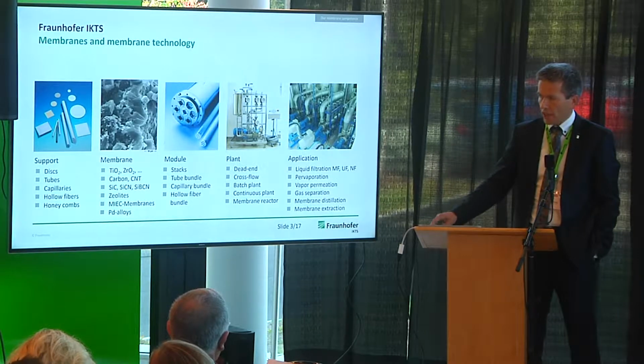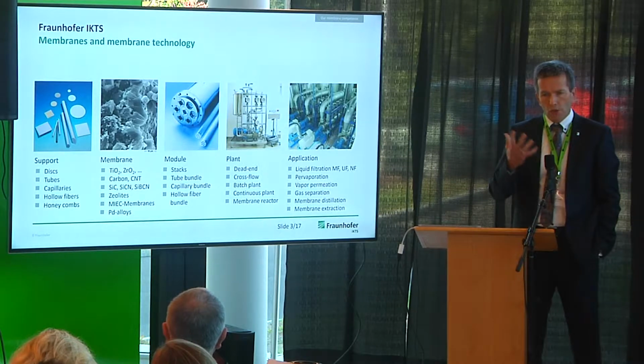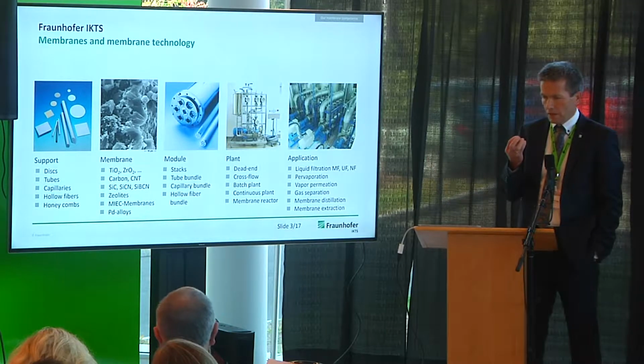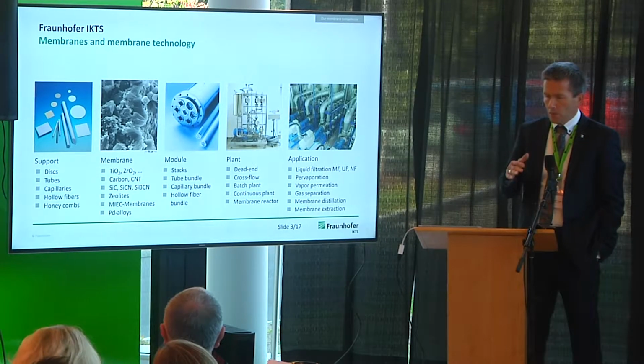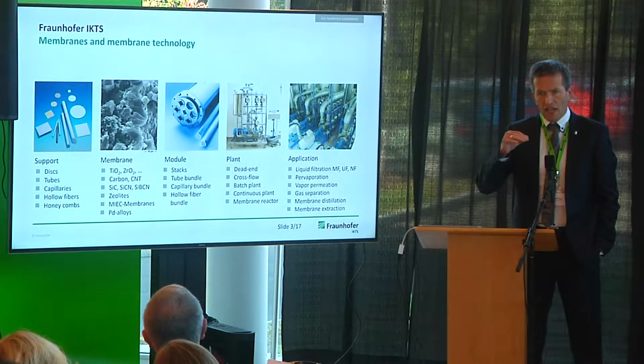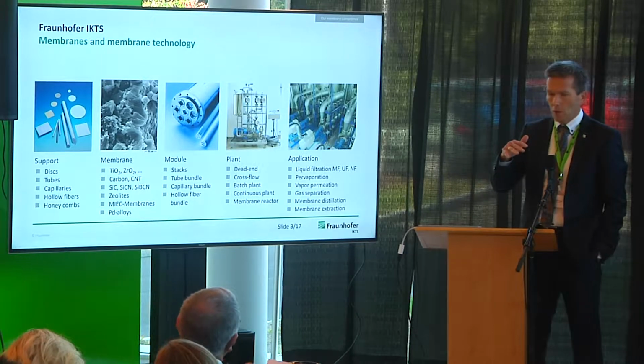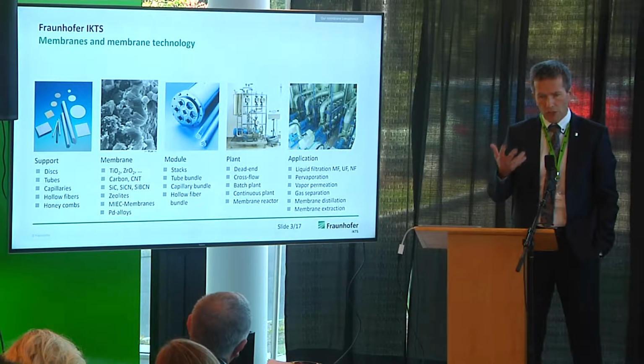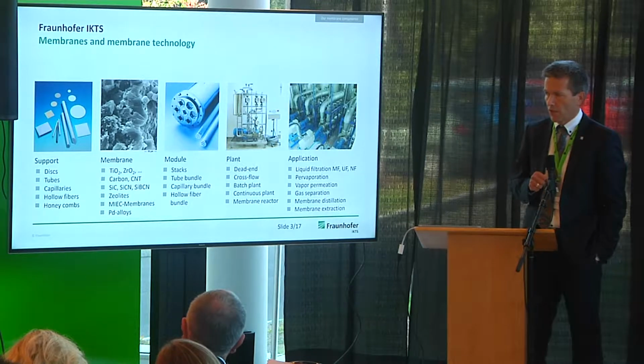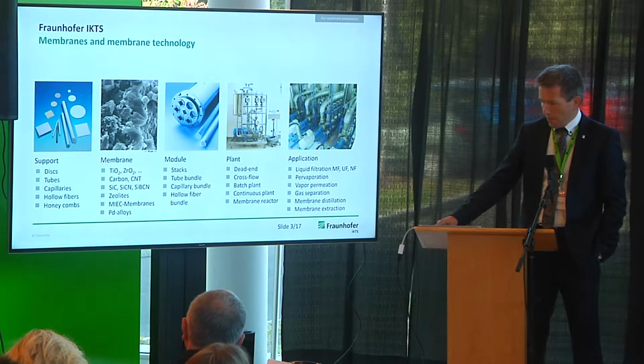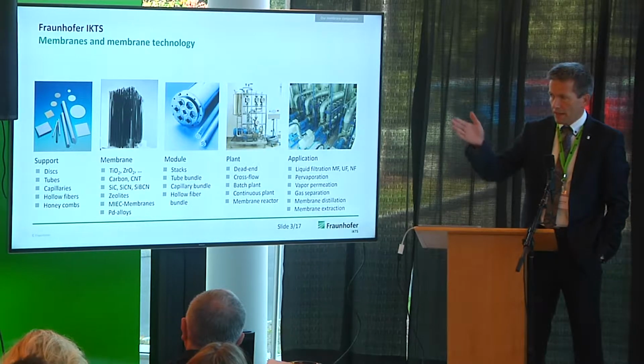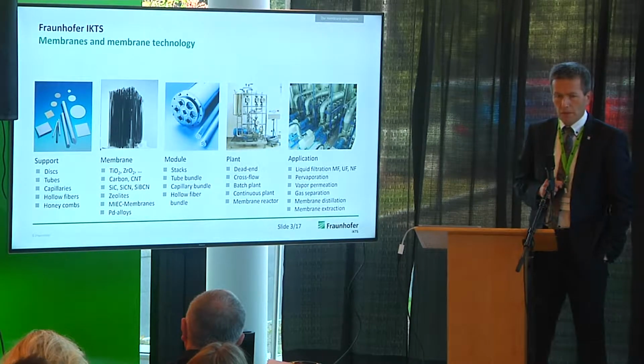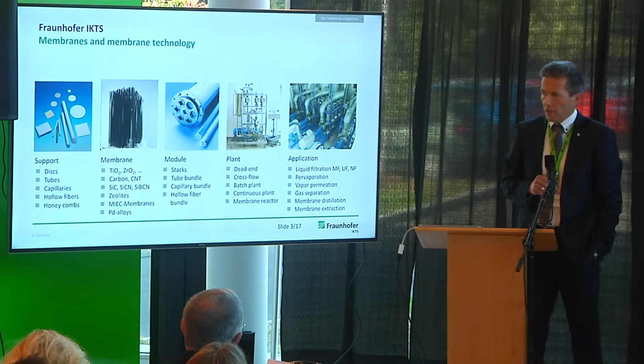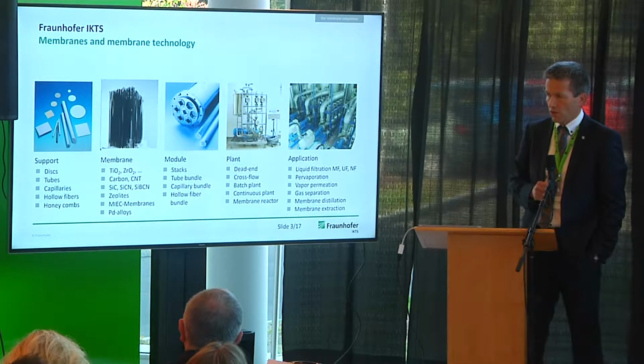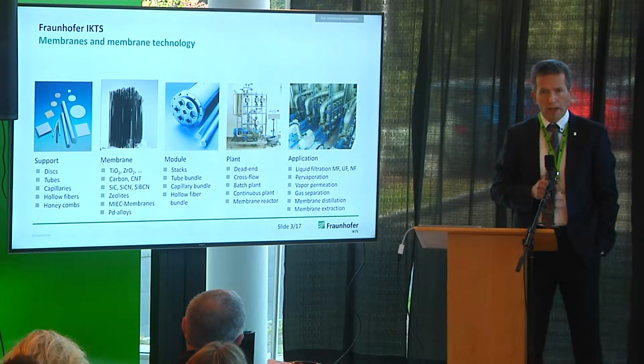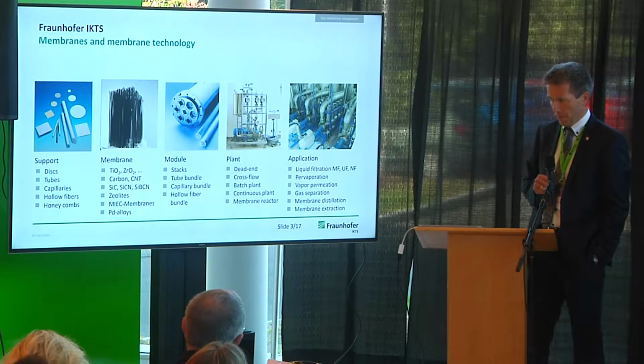The next group is working on zeolite membranes. You know that zeolites have a specific crystallographic cage, and we prepare thin zeolite layers on porous substrates without intercrystalline pores. So we use only the crystallographic pores for separation. We are working on mixed ion electron conducting membranes. This black material here is a perovskite material, which can be used for oxygen separation, or other materials for hydrogen separation. And we are working on palladium and palladium alloys for hydrogen separation.